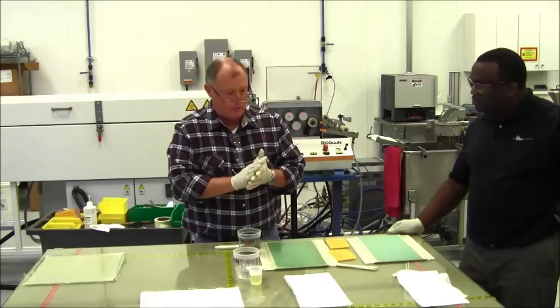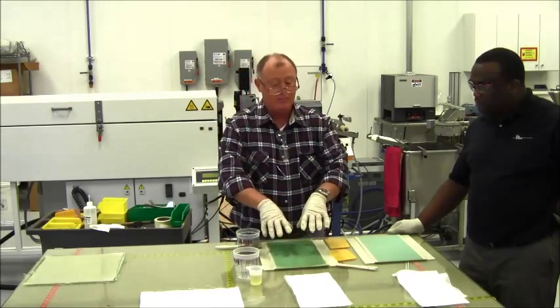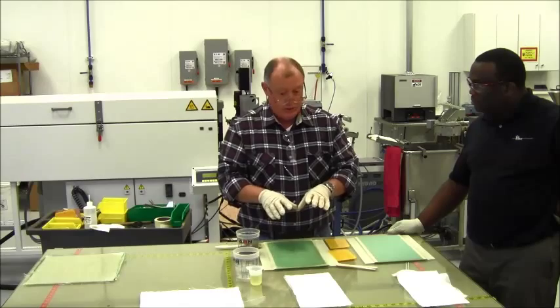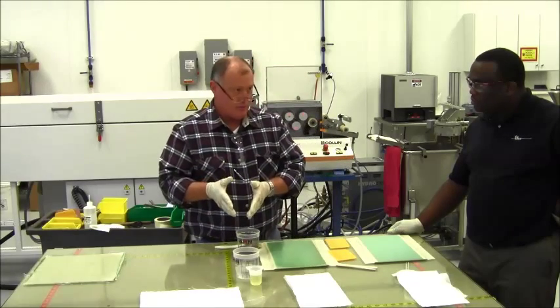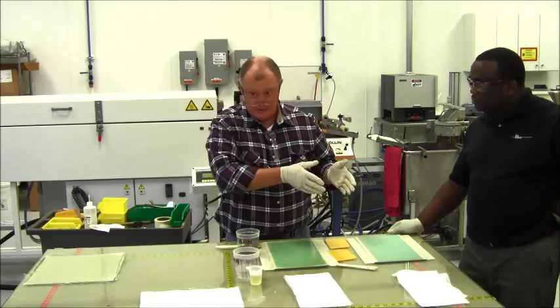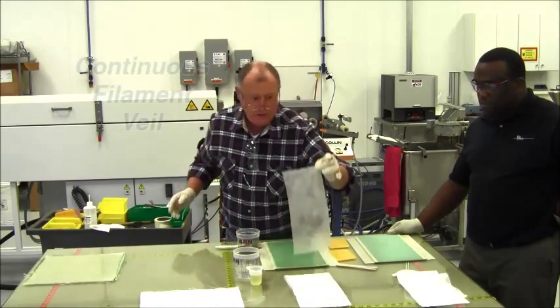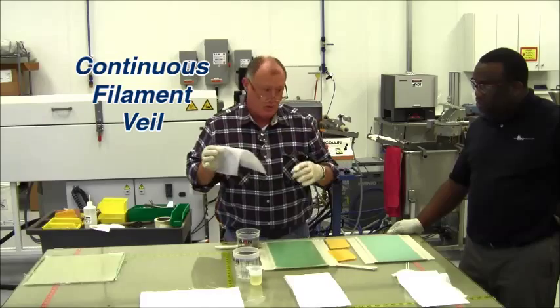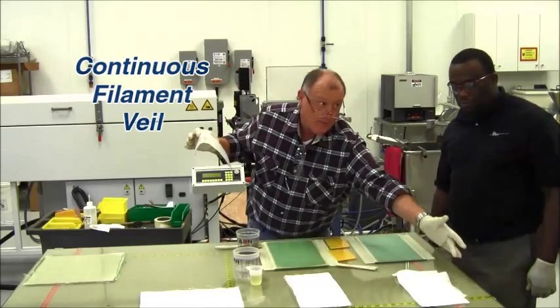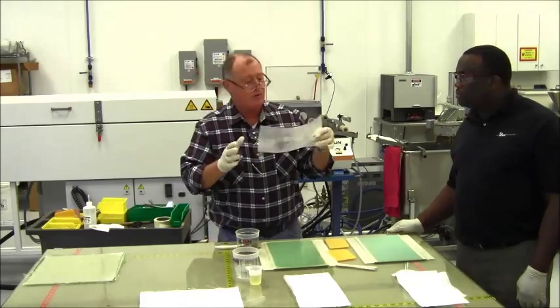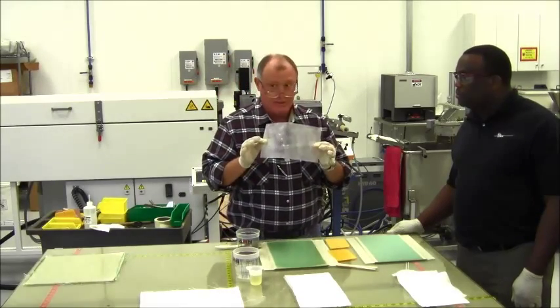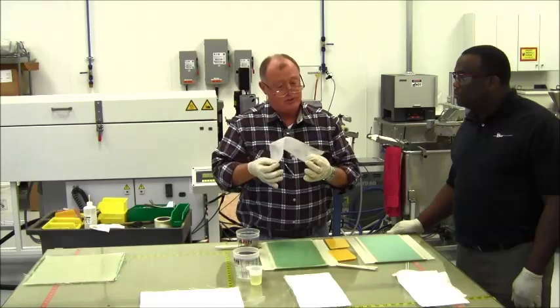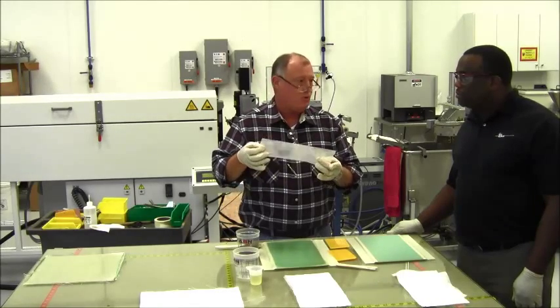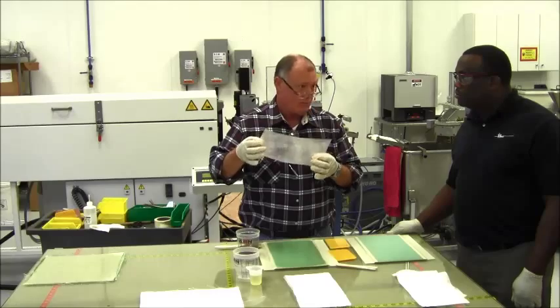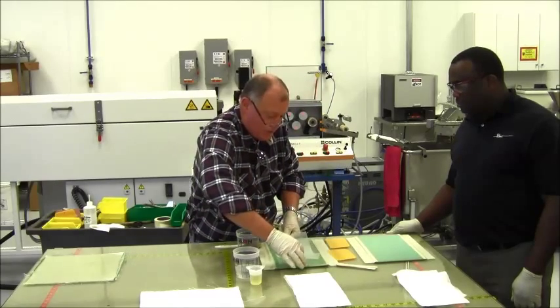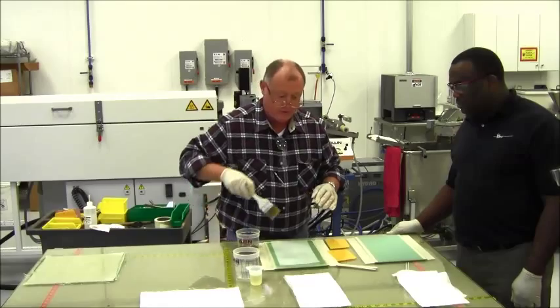In this case, I'm going to use a veil surface again against the core first. But because I'm using a vinyl ester resin, not an epoxy resin, which we'll do next, I've chosen to use a continuous filament veil as opposed to a woven veil like this one. The reason for that is because this veil will actually disappear and give you better aesthetics with the vinyl ester. Whereas if you use this type of veil with epoxies, the epoxy won't break down the binder and it won't wet out properly. So we'll start with that one first, and it will absolutely disappear here in just a second.